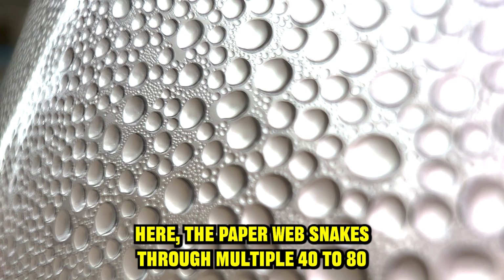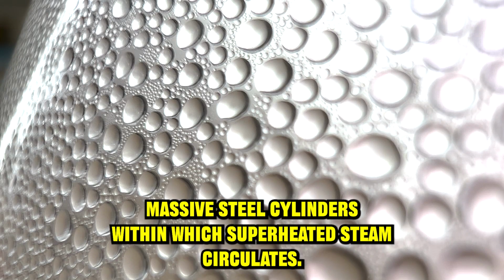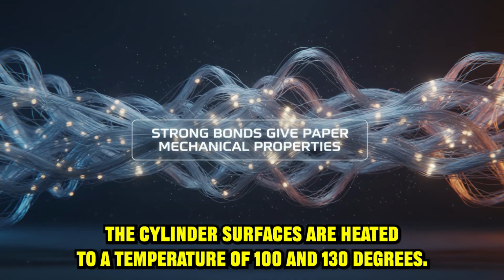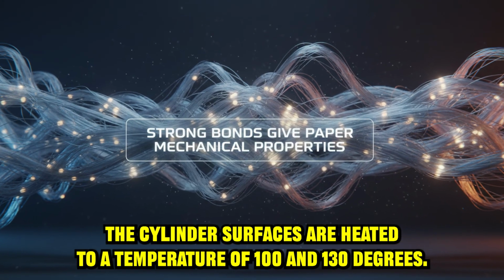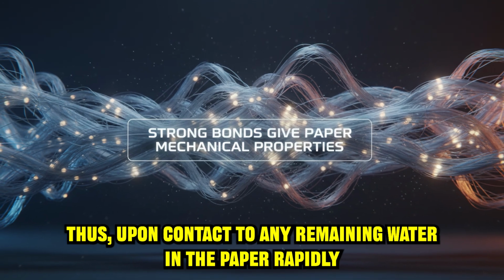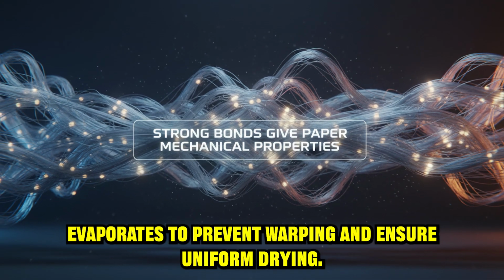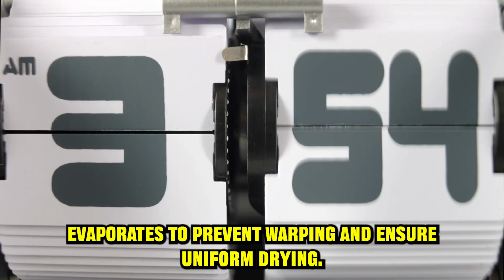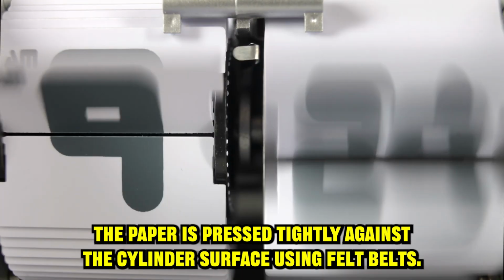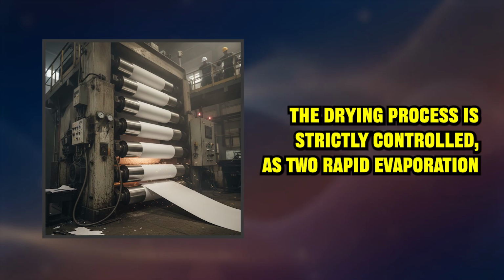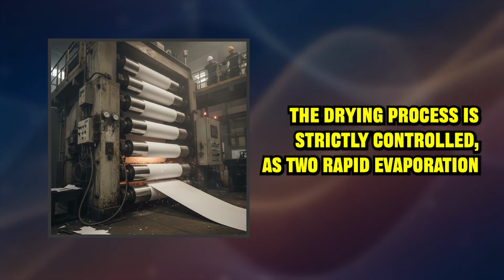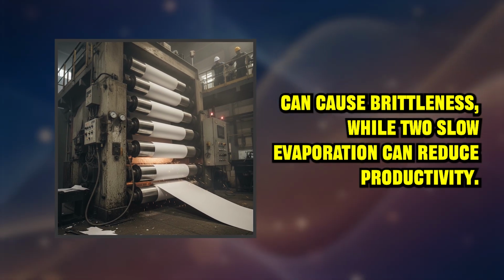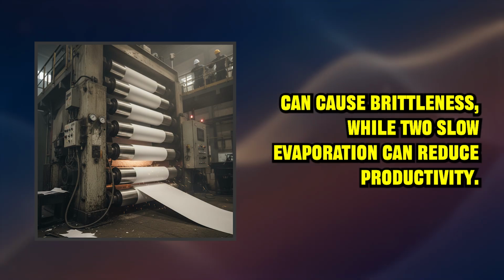Here, the paper web snakes through multiple, 40 to 80, massive steel cylinders within which superheated steam circulates. The cylinder surfaces are heated to a temperature of 100 to 130 degrees Celsius. Upon contact, any remaining water in the paper rapidly evaporates. To prevent warping and ensure uniform drying, the paper is pressed tightly against the cylinder surface using felt belts. The drying process is strictly controlled, as too rapid evaporation can cause brittleness, while too slow evaporation can reduce productivity. Heat is distributed among the sections, allowing precise control of the drying profile.